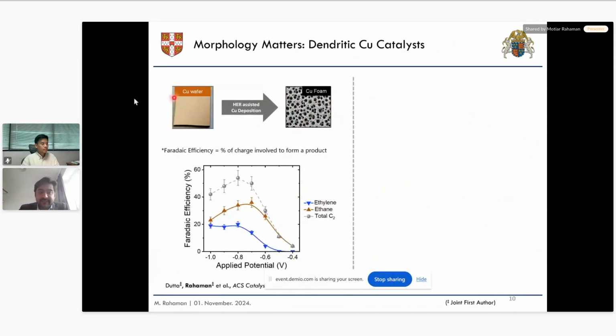For example, if we use this copper foam, which is a macroporous structure, we can get around 55% Faraday efficiency of C2 hydrocarbon. As I said, copper is unique for multi-carbon production. The term Faraday efficiency means the percentage of charge involved to form a certain product, because electrochemically we apply a certain potential, we get current, a certain amount of charge passes through the process, and then we can calculate the percentage of charge which is involved to form a certain product. Here 55% of charge was involved to generate ethylene and ethane, which is a really nice value for selective C2 hydrocarbon production.